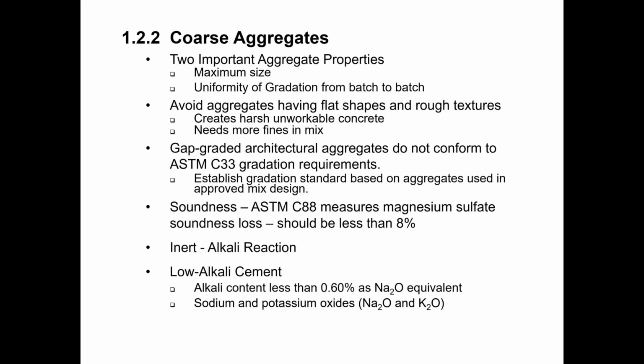All right, another thing to keep in mind to investigate with regard to coarse aggregates is the soundness of the aggregate. So we have ASTM C88, which measures the magnesium sulfate soundness loss of the aggregate. To be a good quality aggregate, that magnesium sulfate soundness loss should be less than 8%.